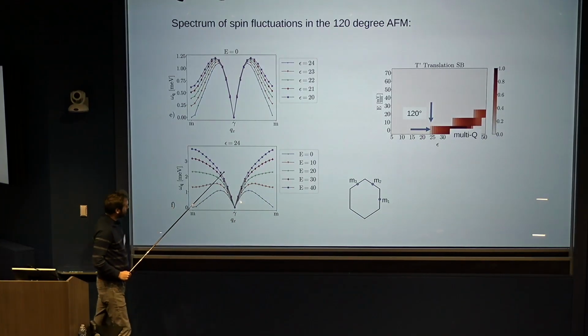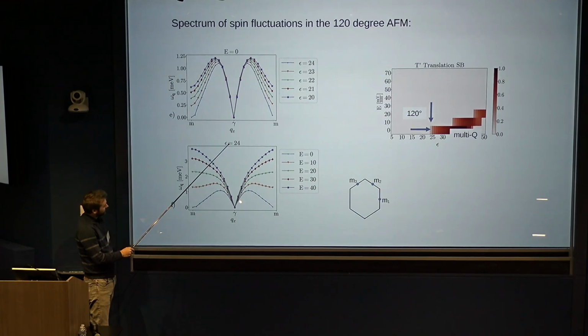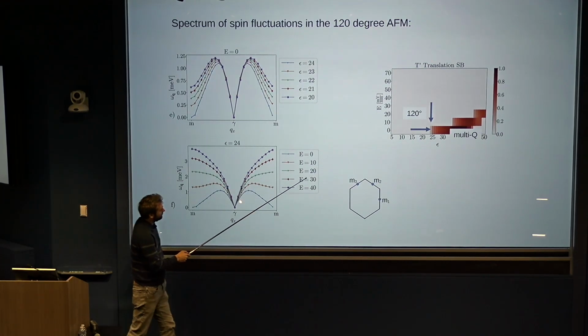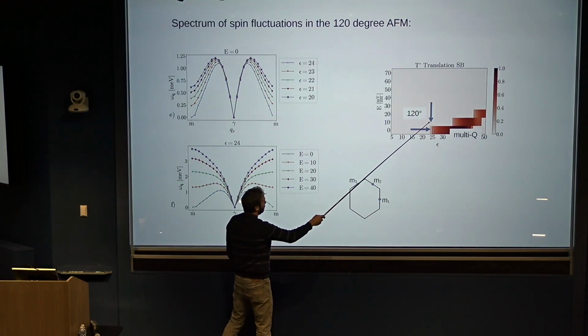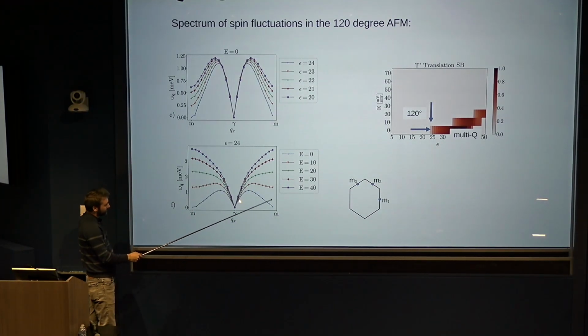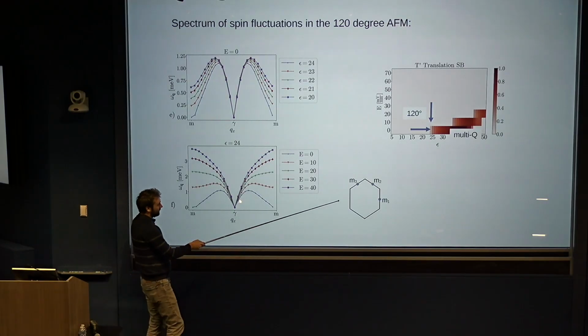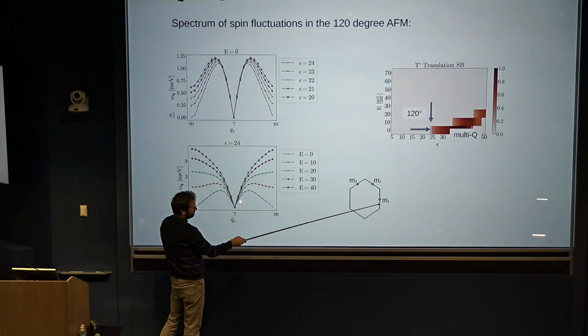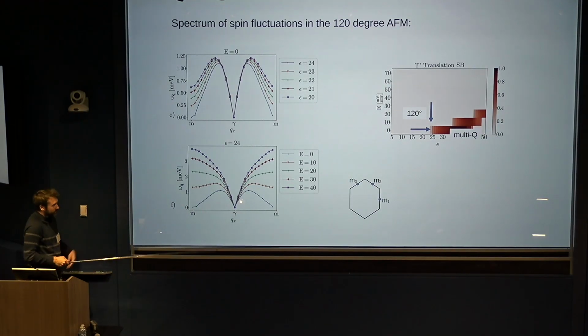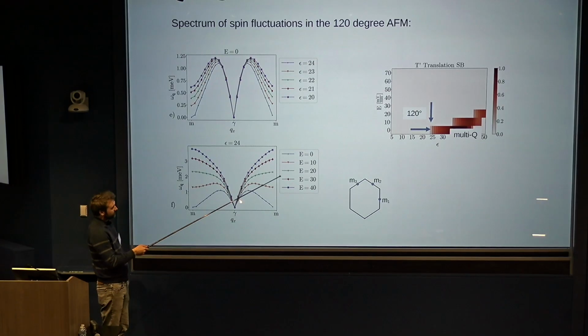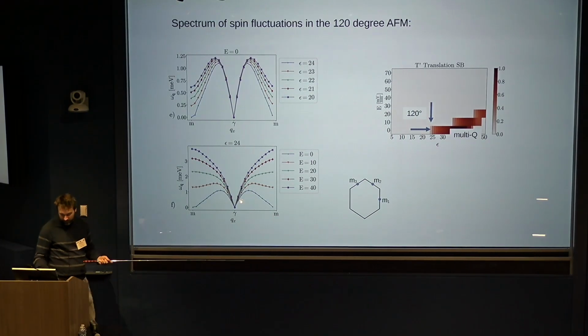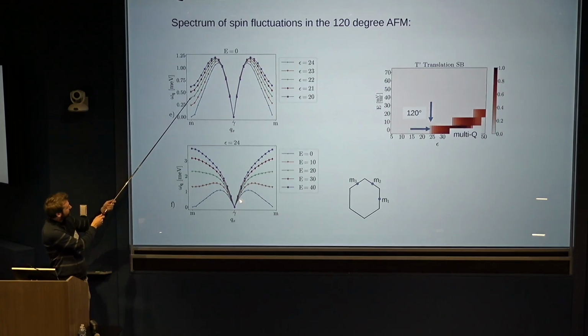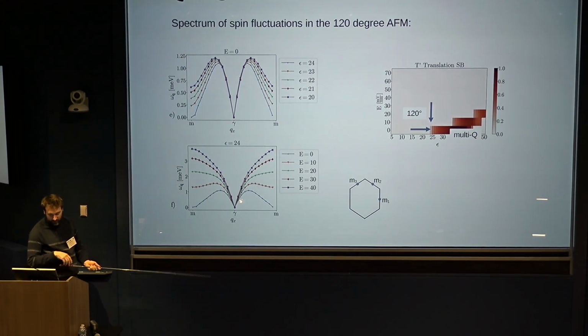And then similarly, if you work at a fixed dielectric constant, but lower the displacement field and approach the transition from here, you also see this lowering of the energy of the spin fluctuations at the endpoints. I'm only showing the behavior here at the M1 point, but we always find that the threefold rotation symmetry is retained, so we have the same behavior at the M2 and the M3 points. So this is just to say that this transition seems to be continuous. And so we see this condensation of this bosonic mode at the endpoints, which are indeed the ordering wave vectors of the static multi-Q order that I was showing previously.